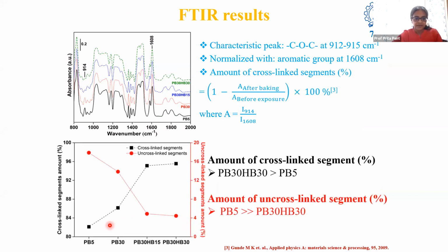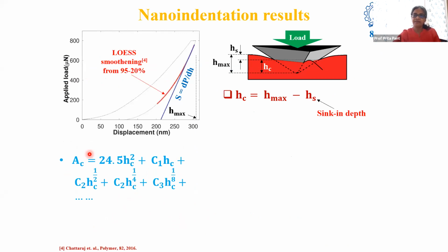And we found that the black here is the cross-linked segments. So in PB5, we've got about 82% cross-linked, whereas in PB30HB30, the most heated sample, we are up at about 96-97% cross-linking. What is interesting is that instead of thinking in terms of these 82%, you think about the amount left uncross-linked. Okay, so there's only 4% left uncross-linked here, and there's about 18% left uncross-linked in this sample.